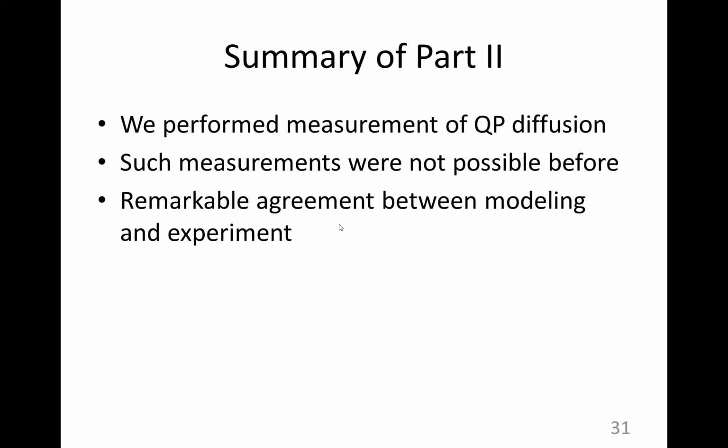And to summarize the second part, we performed measurement of quasi-particle diffusion, and such measurements were not possible before because of the fastness of this diffusion. So we have obtained quite remarkable agreement between the modeling based on the thermal diffusion equation with electron-phonon coupling and the experiment.